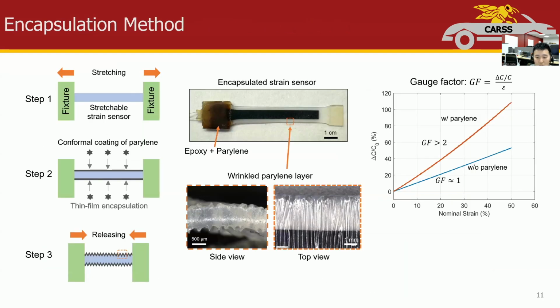To encapsulate the sensor, we developed a stretchable Parylene layer. As you can see on the left-hand side, we first pre-stretch the sensor and then deposit Parylene on its surface.